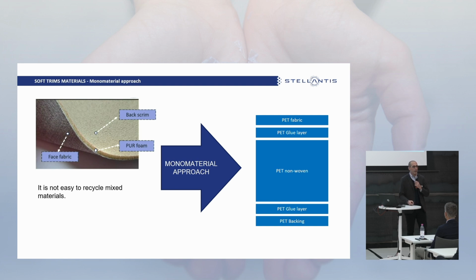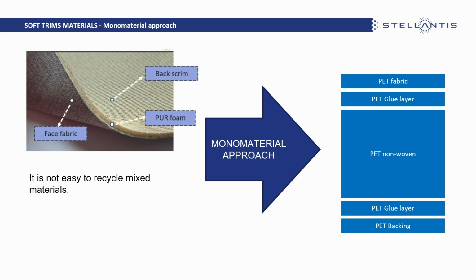What can we do? One possible approach, on which not only us but also our competitors are working, is the monomaterial approach. So to substitute the layer, in the example here, the polyurethane layer that is between the 2 polyester layers, with a non-woven polyester. In this way, we will have the aesthetic layer made of polyester, the layer in between that was before a polyurethane foam made of non-woven polyester, and the backing made again of polyester. This, from the point of view of recyclability, is a very good option.